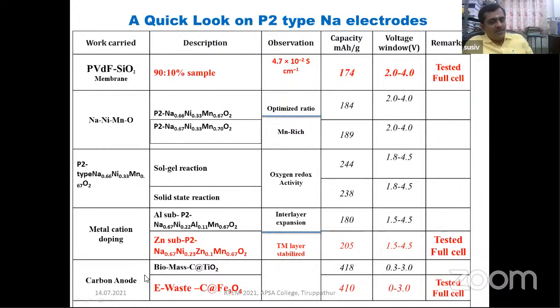And we have prepared some carbon material using biomass coated TiO2, and also we have prepared e-waste. E-waste is nothing but, in the used printer cartridges, we have some powders that have been used as the carbon source. And we have coated that carbon on the Fe3O4, and we made the anode material for this sodium electrode, and it exhibits 410 milliampere hour per gram and was tested as a full cell. Also, this Zn based material has been used as the cathode. Finally we have attained the full cell configuration using this Zn substituted P2 type material, and also e-waste based carbon coated Fe3O4 material, along with the PVDF SiO2 electrolyte film.